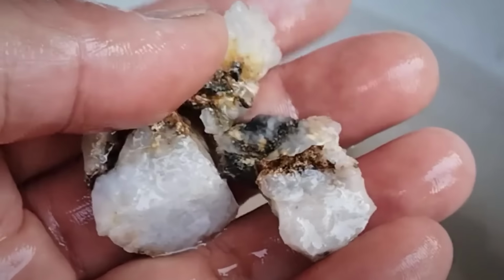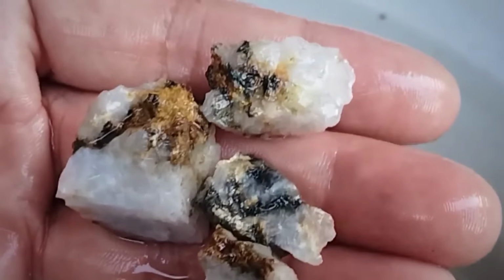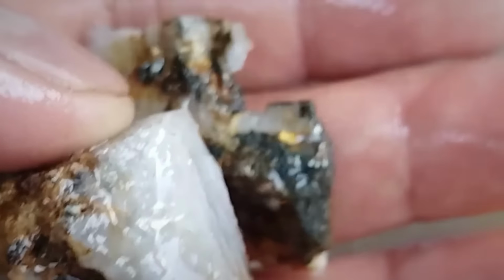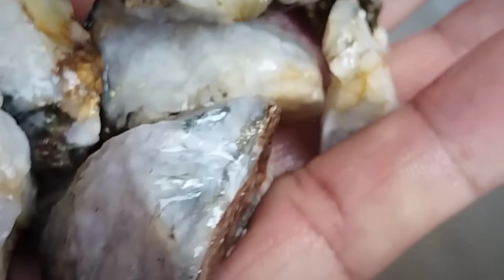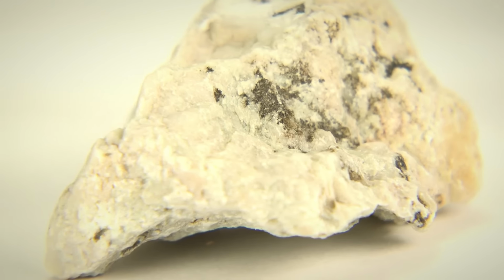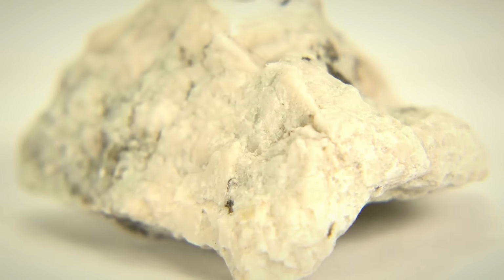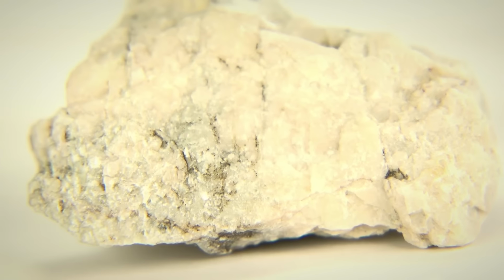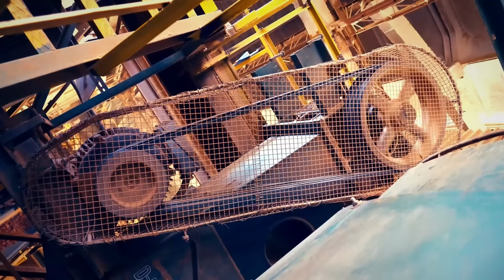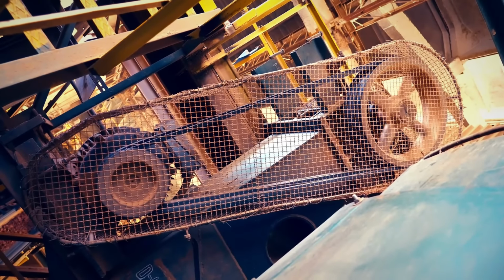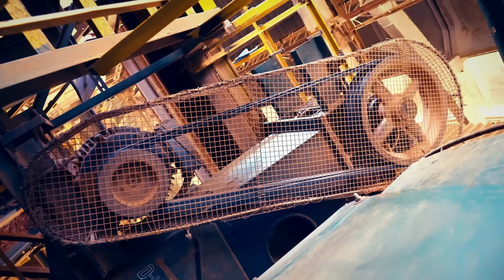However, heating pyrite to 500–700 degrees C in the presence of oxygen breaks it down. The sulfur oxidizes into sulfur dioxide, a pungent, acrid gas, and the iron oxidizes into hematite or limonite. What remains, if you're lucky, is a dark red, crumbly residue with gold specks now released from their sulfide prison. This oxidative decomposition is the entire logic behind roasting. It strips away the iron-sulfur envelope that sealed the gold. But it only works if gold was truly present to begin with. Pyrite without embedded gold is just iron oxide waiting to happen.